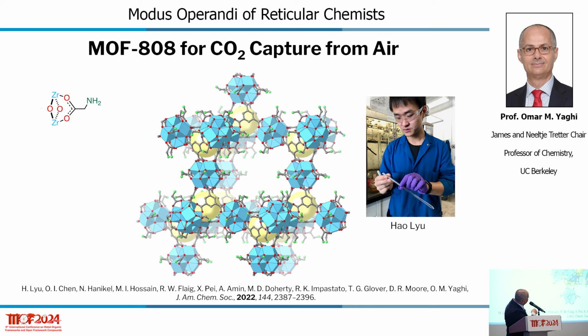This is glycine, and glycine has a carboxylate that binds strongly to zirconium, so it doesn't escape, and there is an amine, a primary amine, that will seek CO2 from air. Okay? And you can see the power of MOFs in that you can functionalize the material post-synthetically with glycine so that the amines are exposed and ready to take up CO2 from air.